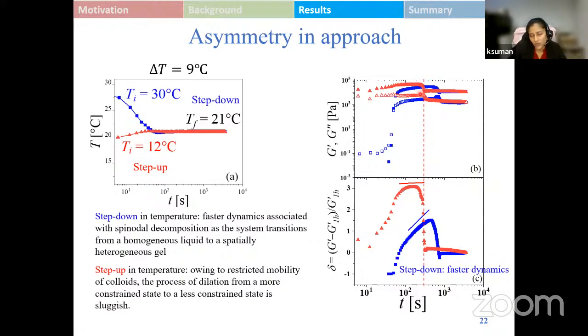We can see that in both transitions, the step up and step down, there is a sudden decrease in the modulus, again followed by an almost constant value of modulus. In order to quantify how fast or how slow both processes are during the step up and step down, we normalize the modulus value using the final value of modulus and plot it as a function of time over here. And we can see that during the step down, there is faster dynamics as compared to the slower step up dynamics in the experiment.